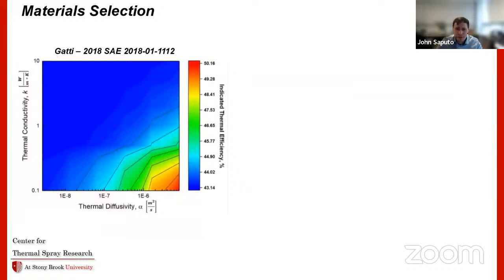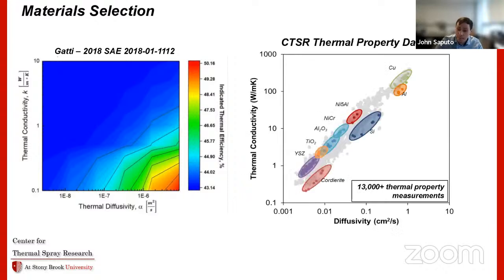So if you look at material selection for what's needed in these systems, I think this is a pretty good study. This is a guy from Wayne State University that did a bunch of conjugate heat transfer simulations of an engine, and just used a huge sweep of thermal properties to see what would be most beneficial in these systems. So I'm plotting thermal conductivity versus thermal diffusivity, and you can kind of see that as you go down to the right, the predicted efficiency gains in these systems goes up.